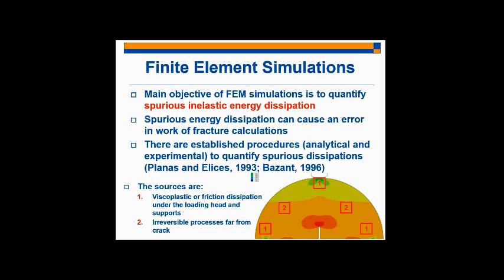And so the work is still ongoing, and we'll further prove this, but we feel very confident basically that the spurious inelastic energy contributions are not too significant. 10% is within the experimental error of our own experiments, which is why we're not considering this value in our tests.